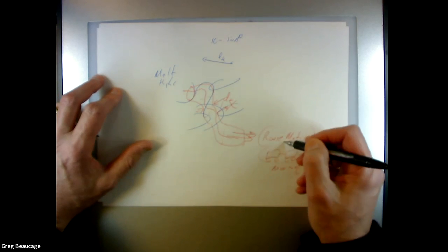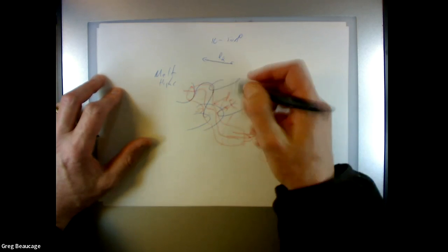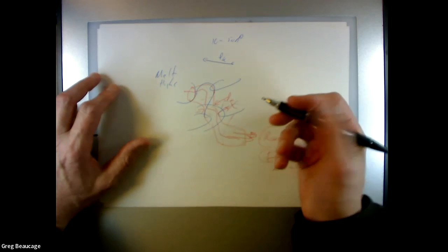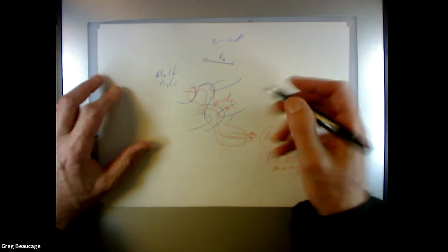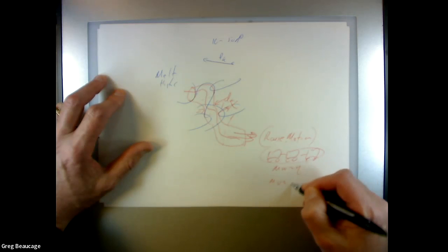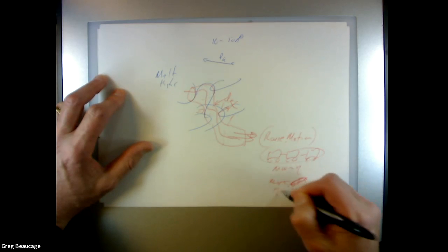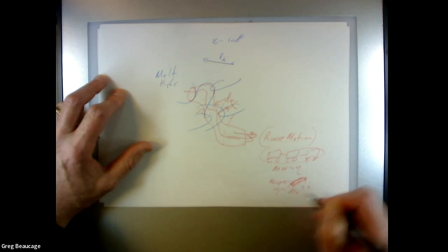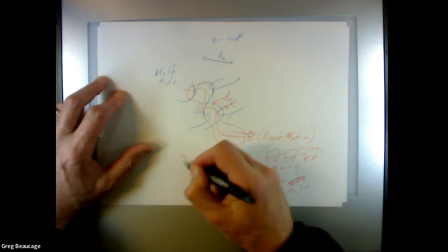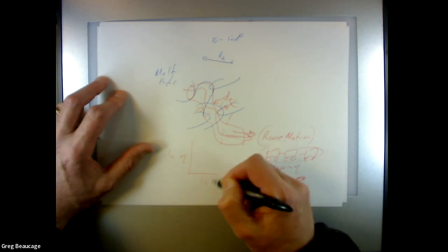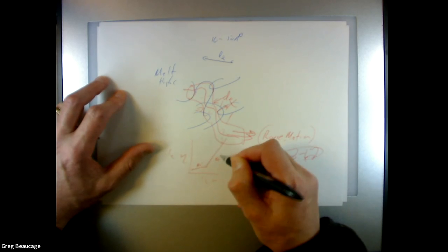So that's Rouse motion. Above that size scale, if the size is bigger than this tube diameter, it's not going to move much at all. It's stuck in this tube. So that's where the viscosity goes with the molecular weight to the 3.4 power, some huge power. In other words, log of viscosity versus log of molecular weight goes up through the roof, and it's pretty easy here. That's the entanglement. So all of a sudden you get a huge impact.